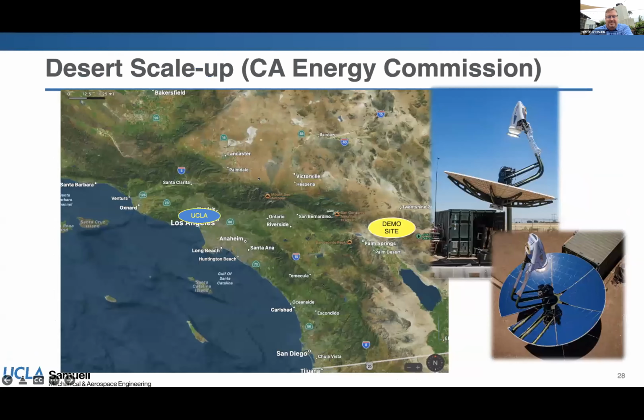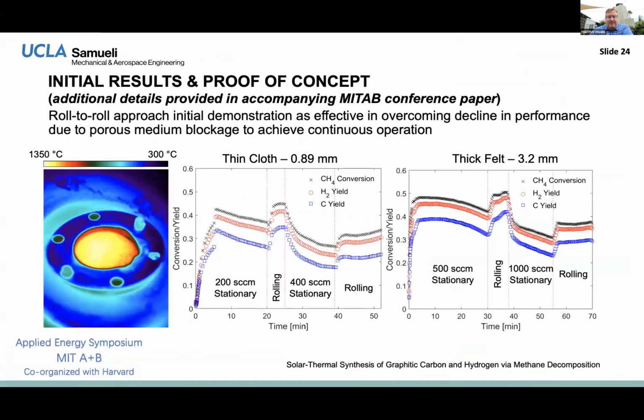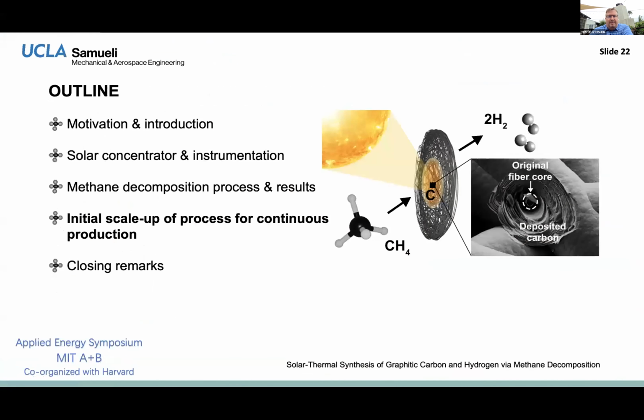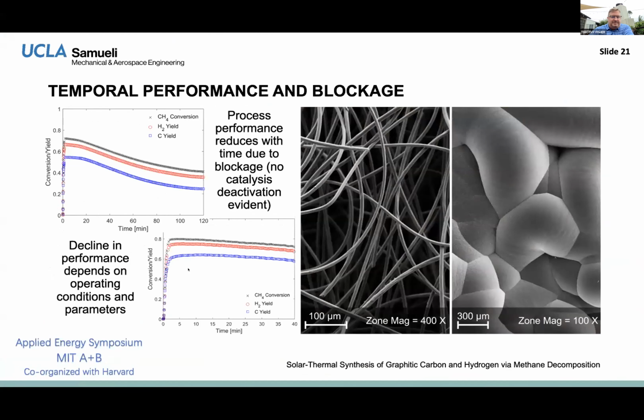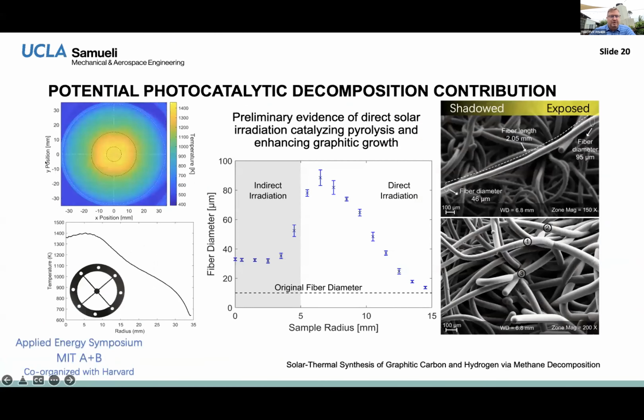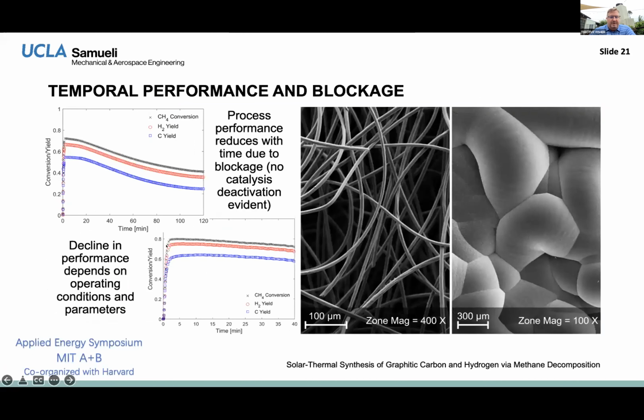And let me go back to a chart. I'll go back to kind of the one. So we get about, this is as good as any. So the hydrogen yields that we're getting, again, you have to take it with a grain of salt. All the reactants are flowing through this porous medium, and so we only have a sweet spot in the middle. But even so, the hydrogen yield is up here above 70%, right?